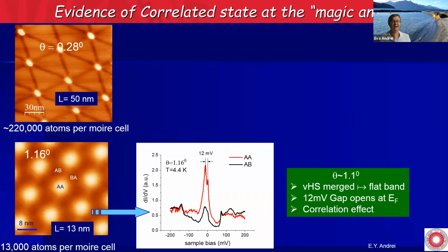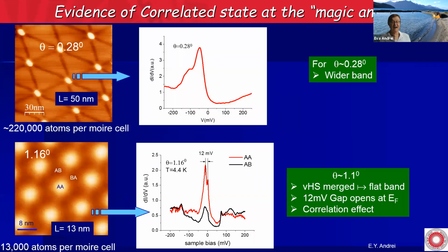This is 0.28 degrees. And you see how this pattern grows. The period now is 50 nanometers. And now the band becomes much broader. Notice that the AA region now has shrunk dramatically, and that's because of the high cost of energy to create them. In the large Moiré system, it's much cheaper in terms of the strain produced to shrink these regions to basically almost a singularity.